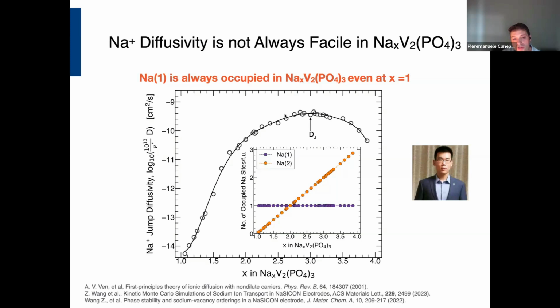lattice of Nasicon. But as you start extracting sodium ions, going all the way to composition 1, the diffusivity drops significantly. And when I say significantly, we are talking about more than 3 orders of magnitude. Remember, this is a log scale. So this is substantial. It tells you that extracting the last sodium, if you were to go below 1 sodium per formula unit, would entail diffusivities even lower than 10 to the minus 14 centimeter squared per second. There is a normalization being done here. If you're interested, we can discuss it.